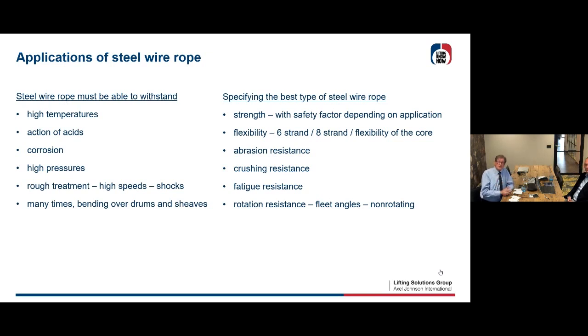So to specify the best type of rope you need, you're going to do the calculation of how much strength you need. In certain applications, you have a safety factor to respect. That depends on the application: overhead cranes, container cranes, and elevators have different safety factors. Sometimes the rope has to be very flexible. You need 6-strand, 8-strand, flexible cores or not. You need to take into account the abrasion resistance, and crushing from ropes on multi-layer drums. You have to consider fatigue.